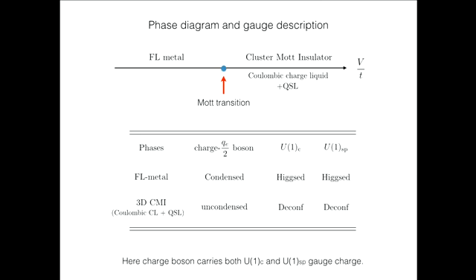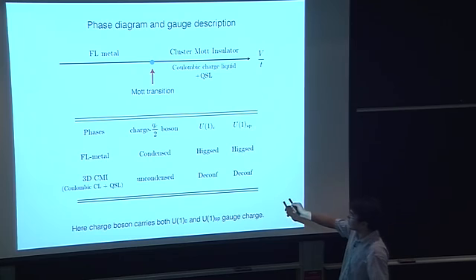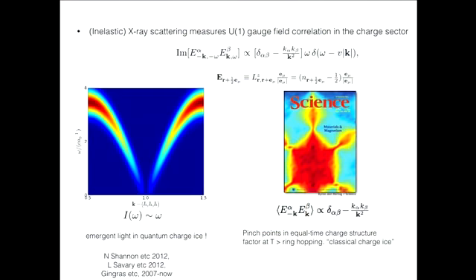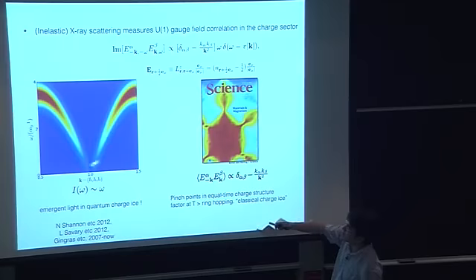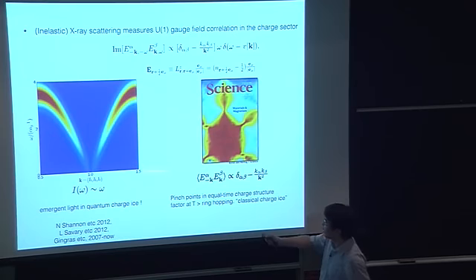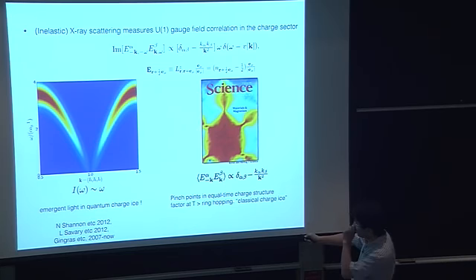So not only is this phase interesting, the Mott transition is also very interesting. In order to get the Mott transition, we need to condense the fractionalized chargons at the critical point. And when the fractionalized chargons are condensed, both the U(1) charge sector gauge field and the U(1) gauge field that causes spin-charge separation are also Higgsed. So one can actually use inelastic X-ray scattering to probe the emergent U(1) gauge field in the charge sector, because X-ray measures the electron density. The inelastic X-ray scattering measures the electron density correlation. So the density correlation will have this kind of emergent gauge photon spectrum. At high temperature, if we kill the quantum mechanics, one can obtain some classical charge ice. We can see similar pinch points, just like a classical spin ice has.